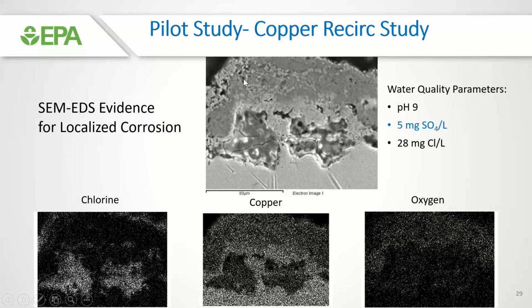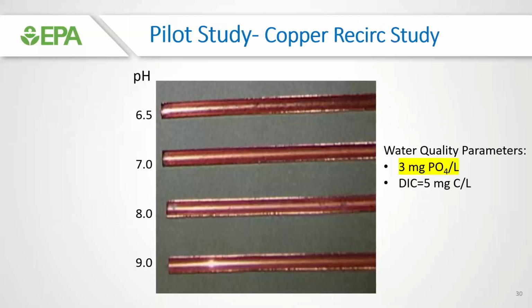And so we see the cap with the sulfate, copper sulfate minerals, and chloride ion. I should have mentioned this earlier, but chloride is always at the base of these things and is always actively accelerating and keeping the corrosion process moving along. Phosphate, strangely enough, what do you know? With phosphate, we don't see those pits form. We didn't see the pit caps form. We didn't see any signs of pitting corrosion in low DIC waters at high pH.